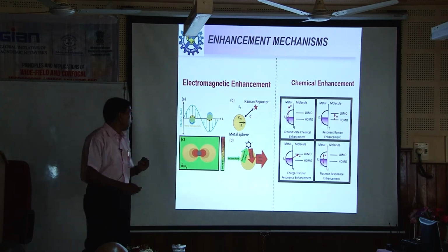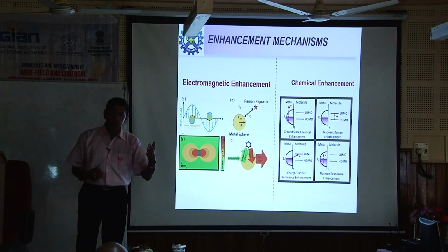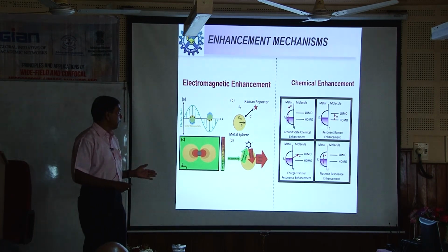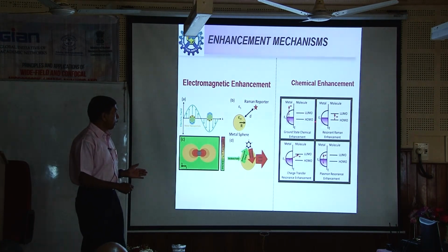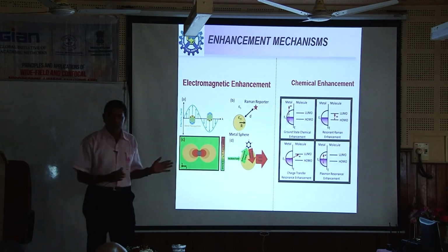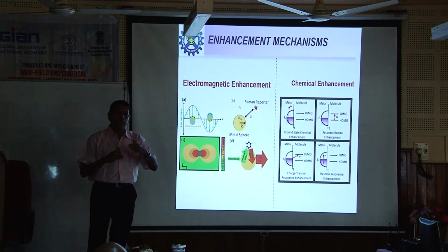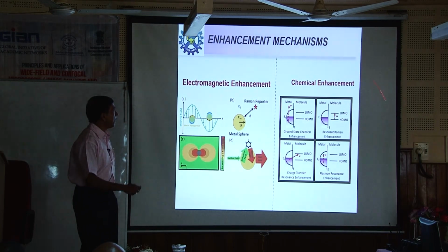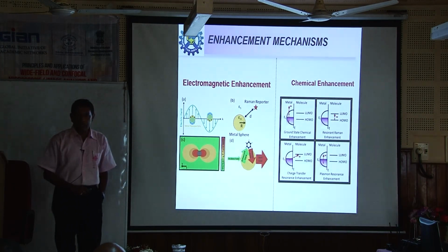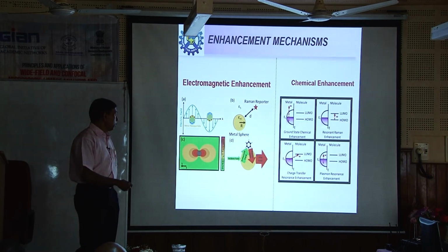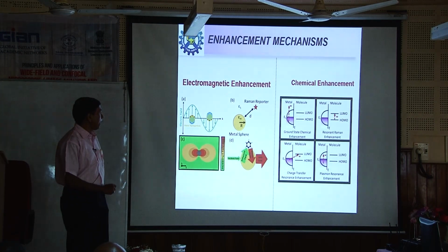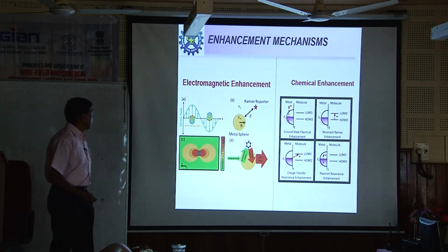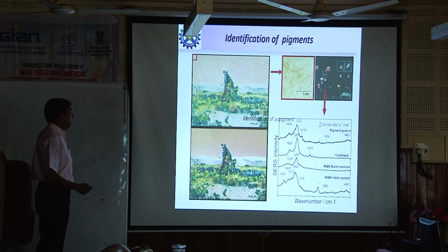called physisorption. Out of which, the molecular energy level or molecular orbital, if you come across it, the highest occupied molecular orbital and the lowest unoccupied molecular orbital, you may tune it and get the closest band gap, and you may tune the enhancement through your chemical enhancement way. So, these are the two theoretical aspects people believe give this enhancement. So, this is one of it.